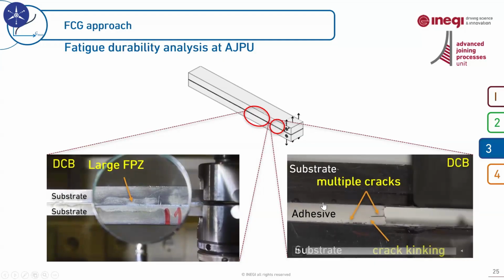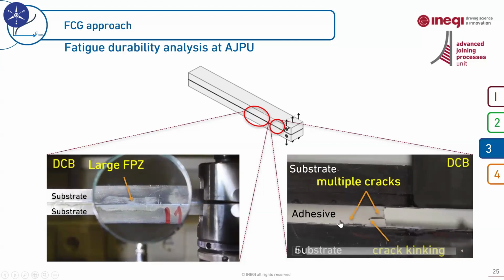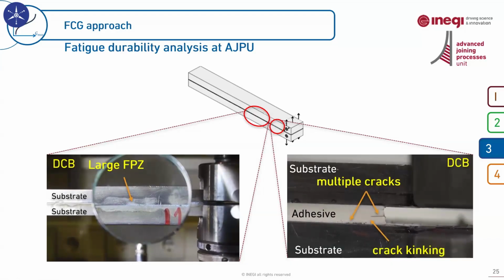It is not possible to see in this video, but we have a very large process zone here, a damaged area, where a crack is not actually created yet, but in the following cycles, another crack is created here, and several other cracks.